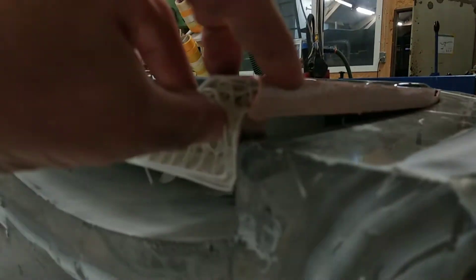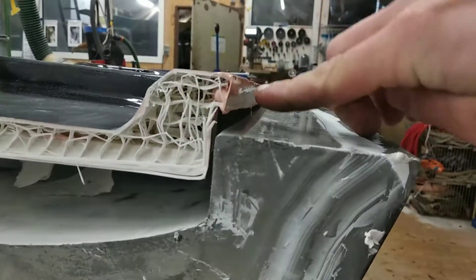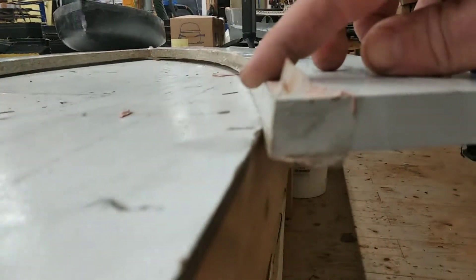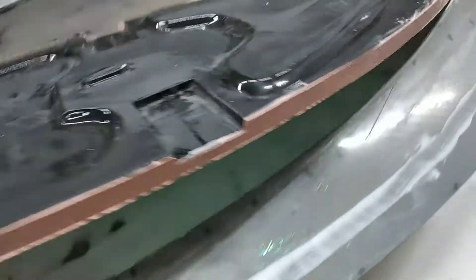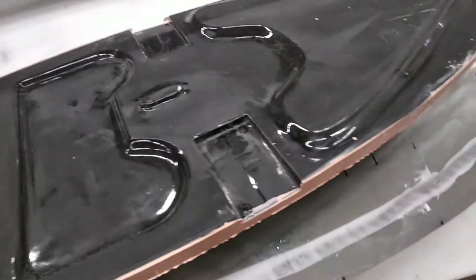I have made this flange not really straight, so what happens is the hull can now slide on top of that and we have a pretty big bonding surface. To achieve that I took this piece of wood and used my jigsaw to cut straight around here at an angle of about three degrees, and then with putty and tape — just usual release tape or packing tape, everything will work — you don't need any release agent and you have an awesome finish.